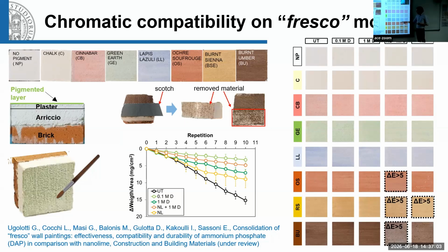Usually, a color change up to a certain threshold, 5, is considered acceptable. So you have your monument, you apply your conservation treatment. If the color changes a little bit, up to 5 of this certain parameter is considered acceptable. A higher color change like this one wouldn't be acceptable because the material is becoming too whitish compared to the original color.